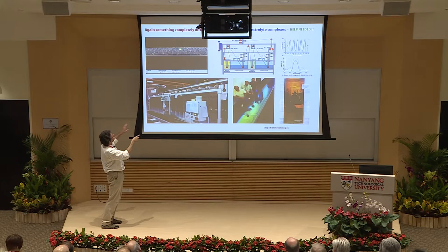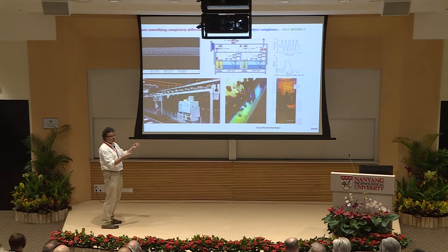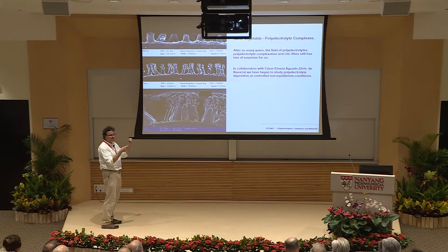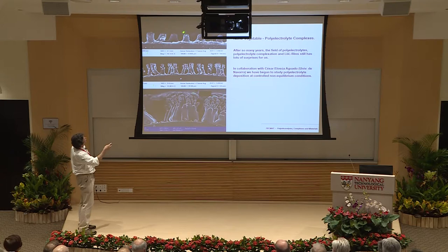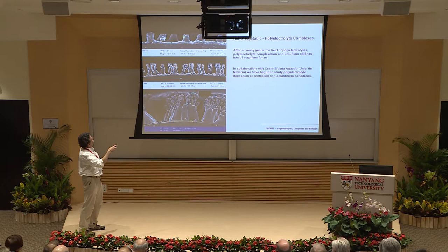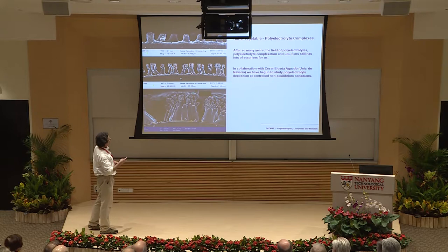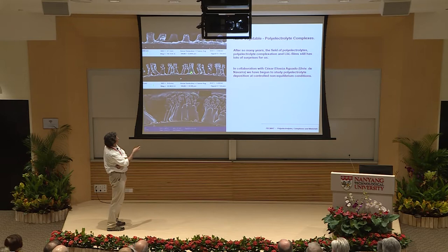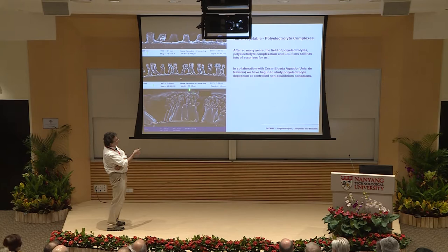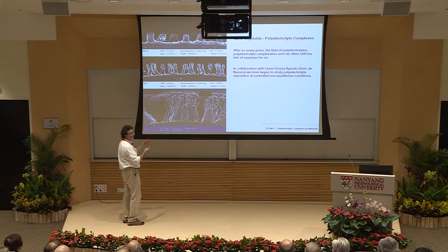Welcome to our nano vegetable garden. This is a film made by dipping in César's lab. In the beginning we have little columns forming — at about 20 layer pairs. At 200 nm scale, the columns have a width of about 250 nm. These little broccoli structures at 80 layer pairs are budding, and they all have the same height. Continuing to 500 layer pairs gives columns 15 microns in height — real nano-vegetables growing, all at the same height.